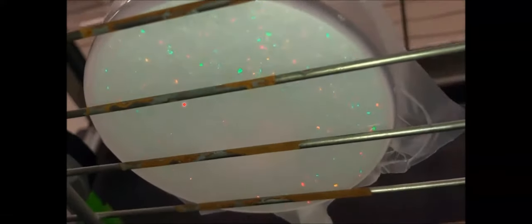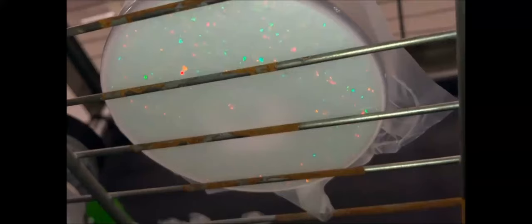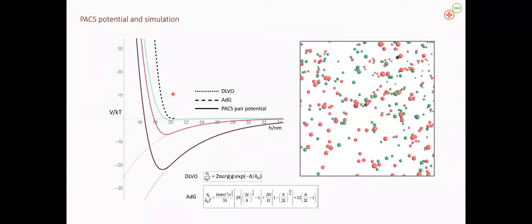When we tune conditions just right, only a few nuclei are produced so that those nuclei eat up all the particles. And we can see that these uniform areas of color, these are each a single crystal with millimeter size domains. Now I'll speak just briefly on the actual math behind it, the theory behind this interaction. Because it's such, I would say, basic colloidal components and very well studied colloidal components that we can really go back to like first principles and describe it thoroughly and be confident that these are really what the energy landscapes look like. And so first I have my attraction, which is given by DLVO. And all these variables, for the most part, can be taken from a conventional zeta sizer. You just get your surface charge and your size of the particle, and then we know the salt concentration, and that's going to tell you the electrostatic potential.